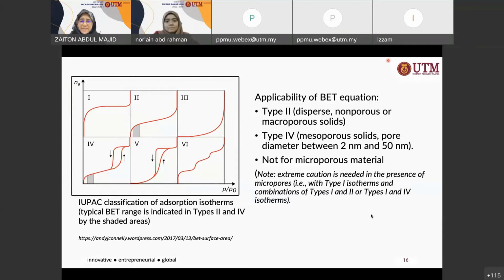Previously in Bicara Pakar, we talked about physisorption isotherms. There are 6 types of physisorption isotherm based on the IUPAC classification. But where is the BET equation applicable? We always run our BET equation, sometimes we do get good results, sometimes we cannot get any results, we get very low surface area and so on. So basically, the BET equation is only applicable for type 2, which are dispersed, non-porous or macroporous solids, and type 4, mesoporous solids, which have pore diameter between 2 to 50 nanometers. So the shaded area here is the BET range.